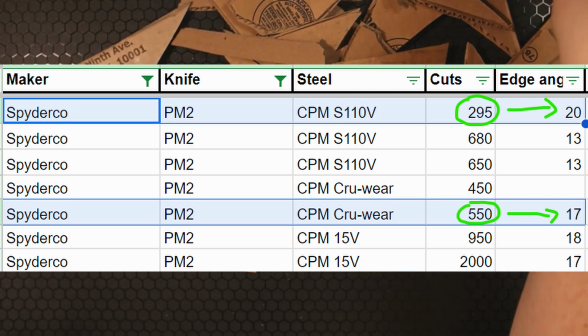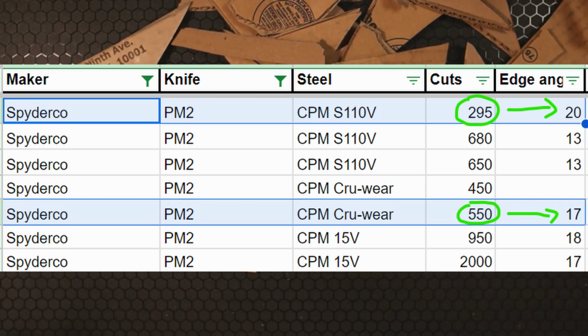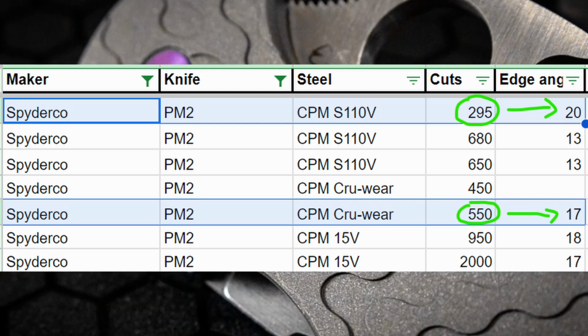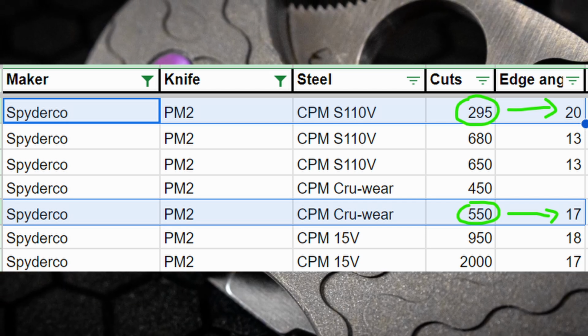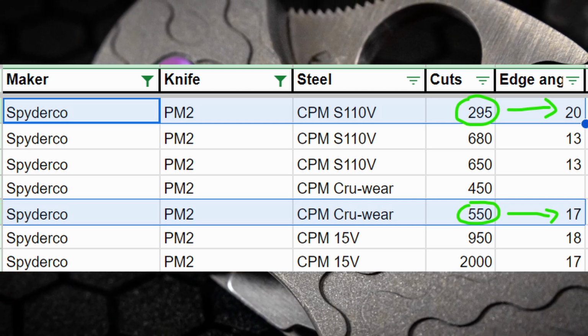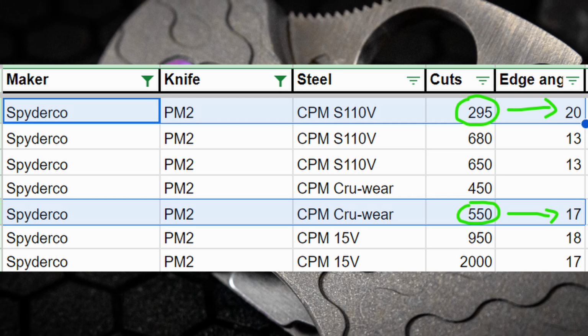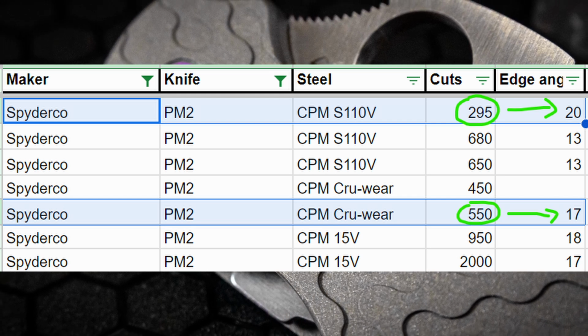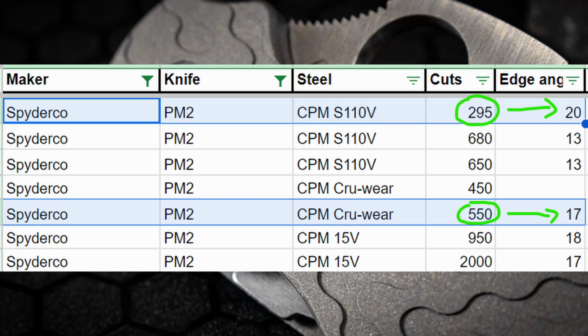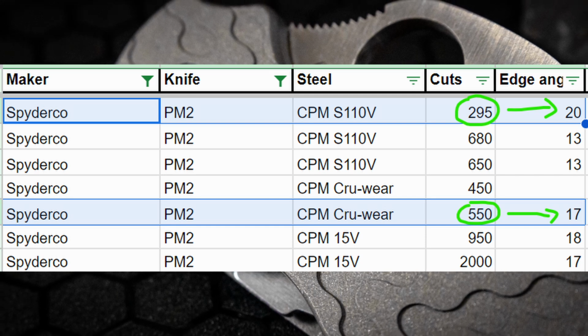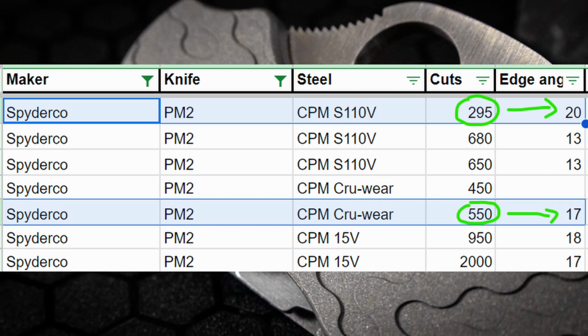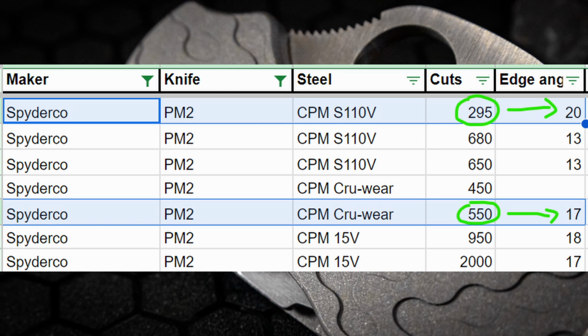The PM2 in S110V, despite having the much better wear resistant properties, was only sharpened to 20 degrees and only achieved 295 cuts. In fact, the S110V had to have its edge lowered all the way to 13 degrees to outperform its CruWear counterpart, and even then only marginally, given its lack of toughness and stability at that much lower edge angle.